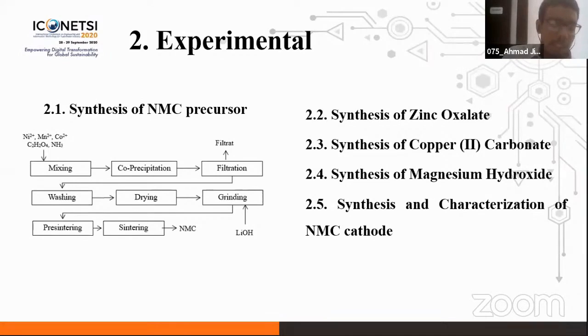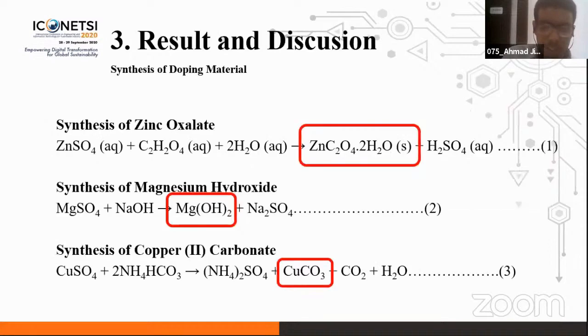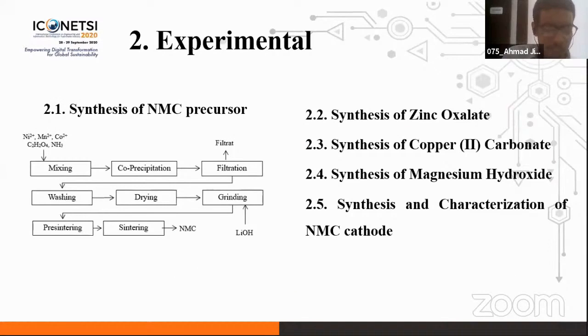And the last is synthesis and characterization of the NMC cathode. Lithium hydroxide and the doping material were added to the NMC precursor and then ground and mixed. The mixture was heated in the furnace and sintered under flowing oxygen. The mixture was crushed and the XRD pattern of the sample was analyzed using an X-ray diffractometer.